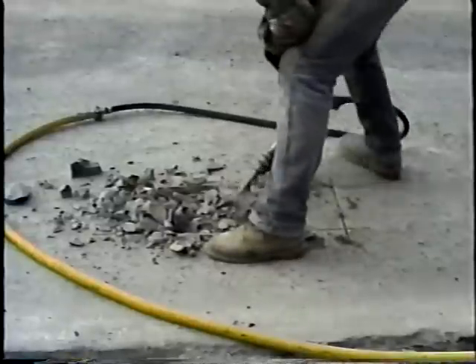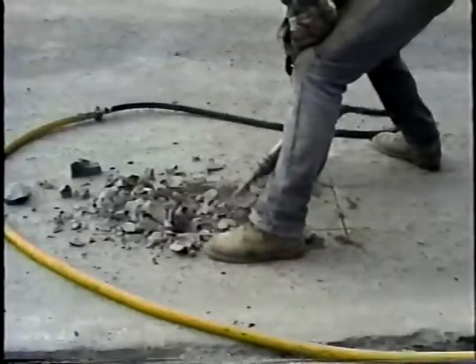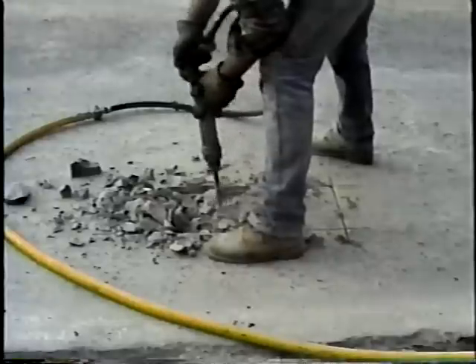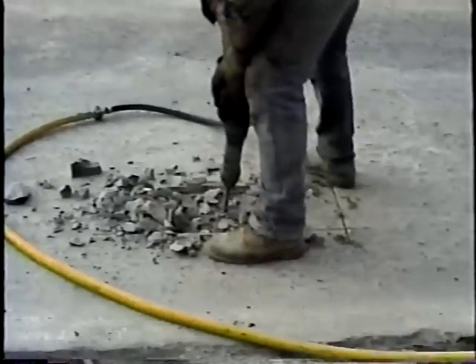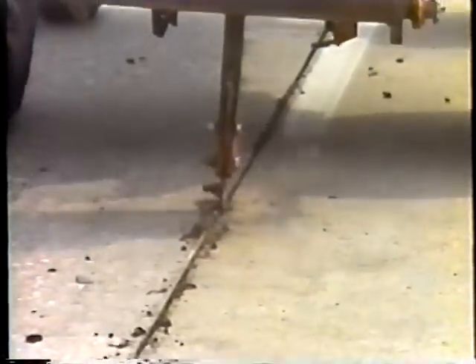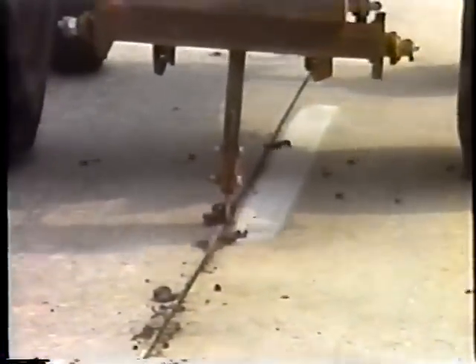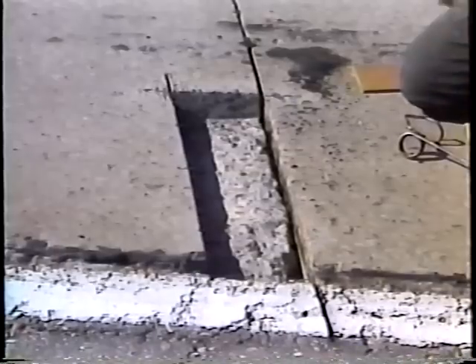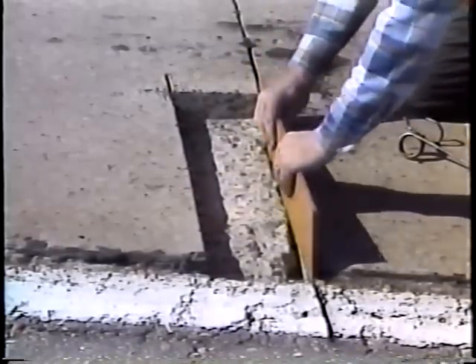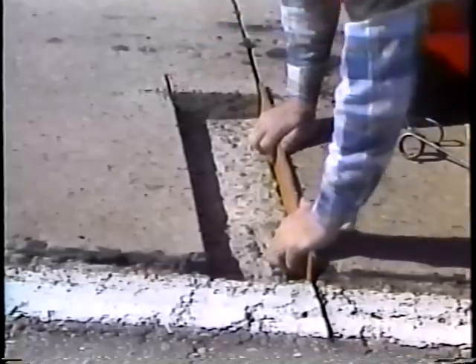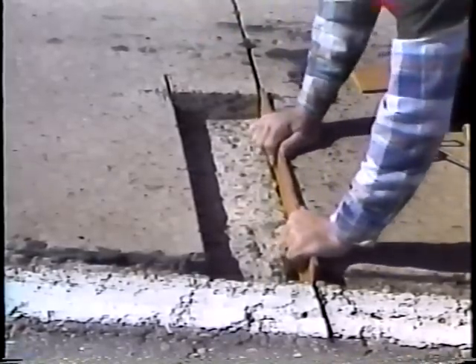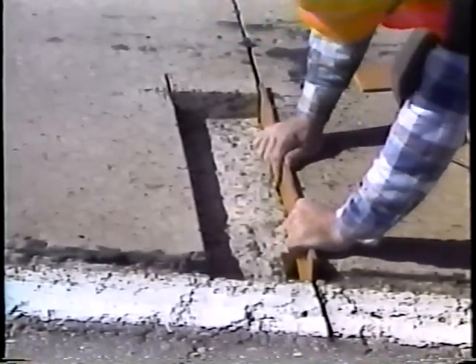And those are the surface preparation requirements when the repair is made in the middle of the slab, away from joints and cracks. At joints, however, there's an additional requirement. The existing sealing material must be removed to prevent its contaminating the repair material. At both joints and cracks, a compressible insert is required. Its purpose is to prevent the repair concrete from intruding into the crack or joint.